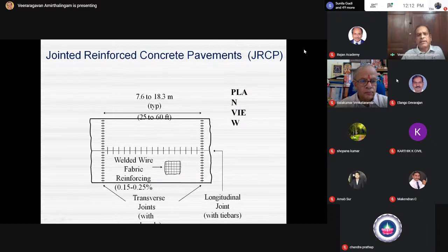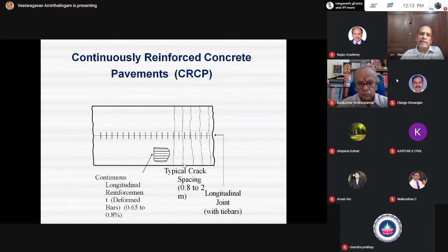We can also go in for jointed reinforced concrete pavement, wherein you can have a skin reinforcement. This is a welded wire fabric reinforcement mainly to take care of the thermal cracks, nothing more than that. It does not add strength. But thermal cracks will be lower. Generally, we don't go in for this reinforced concrete pavement. JRCP is not done. Either we go for jointed plain concrete pavement, or you can go in for a